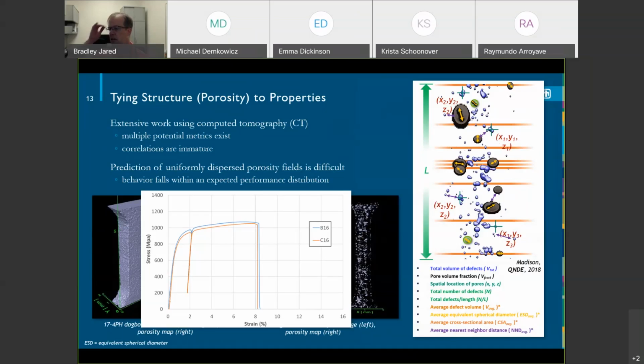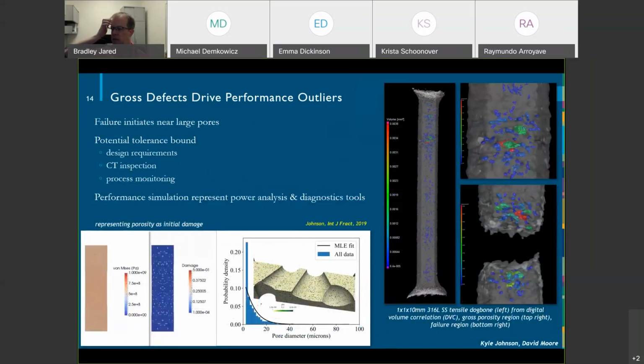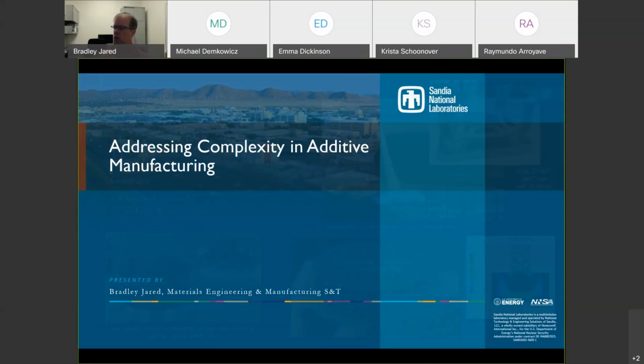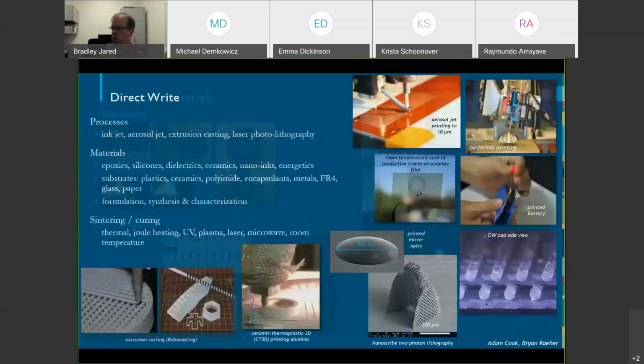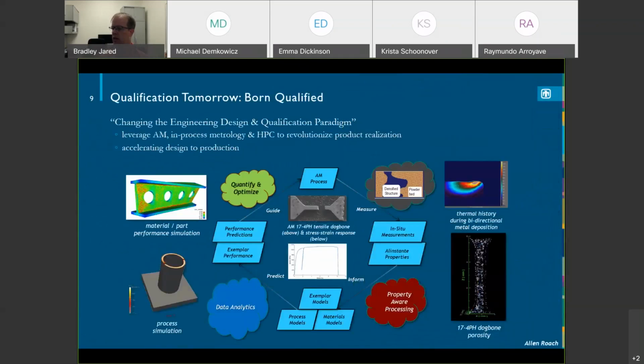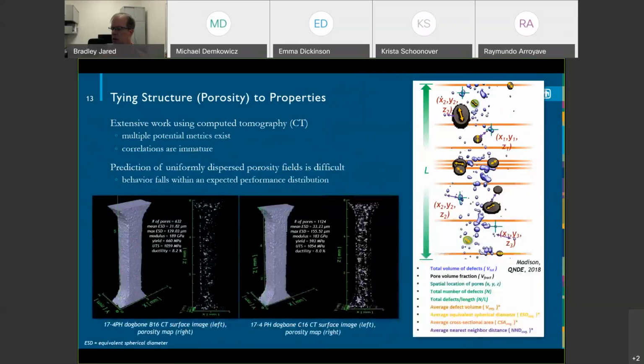And it turns out, what happens in this space, and this is some other work, so this is 316, the previous slide was 17-4, you really start getting into the models are really important and valuable. So Kyle Johnson's done a ton of work here at Sandia in this space with another Sandia and John Emery. And what happens is if you have large gross porosity, right? So if you look at, whoops, oh, that's not what I wanted to do. Apologies, the wrong slide.